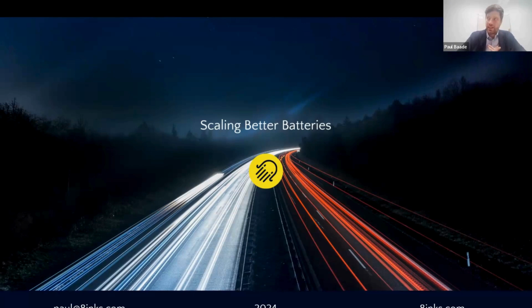I'm not sure. So cycle life depends a lot on the product, right? LFP electrodes are much better than the silicon anodes that we tried. I don't think our silicon anodes are at commercial quality yet, because there's much more than just the coating technology, but also good material. We work with metallurgical silicon SiOX. We get a few hundred cycles out of those types of silicon anodes, but it really depends then on the specific material combination and layups.